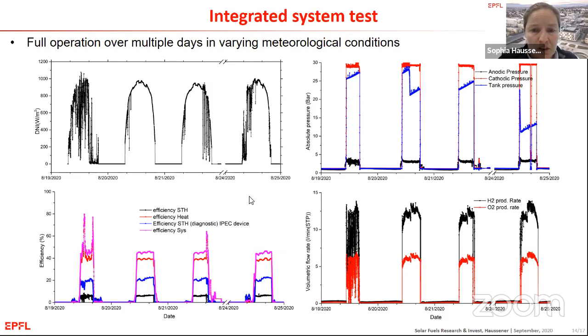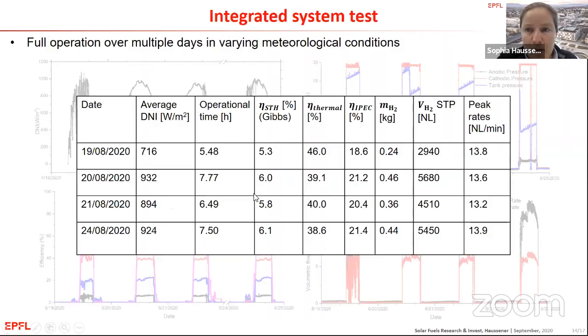So you can see in the table here a summary a little bit. Particularly I want to point out the production rates. So the best day, almost 930 DNI, 7 hours of operation, and we're producing almost 0.5 kilogram of hydrogen, which is enough to drive your car for at least 100.